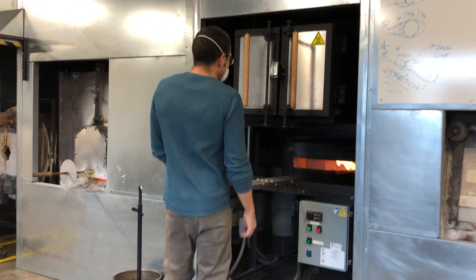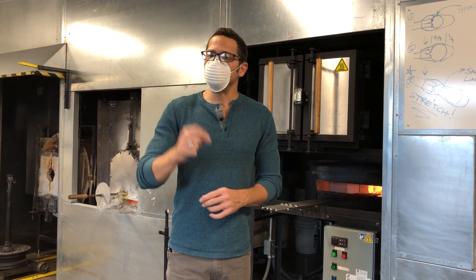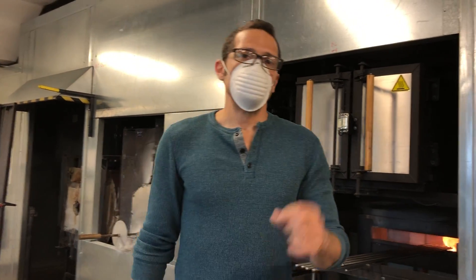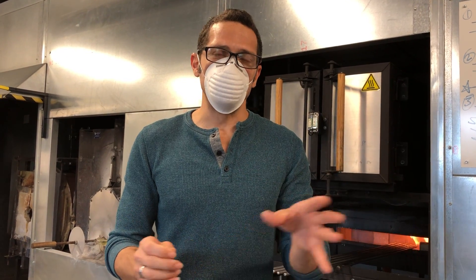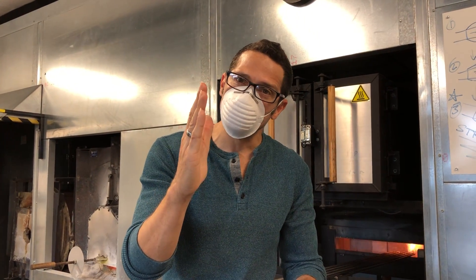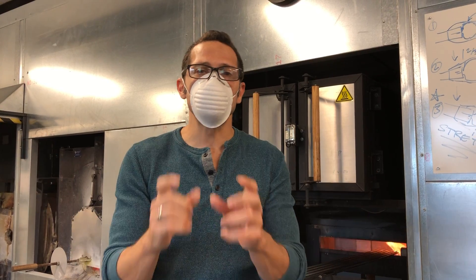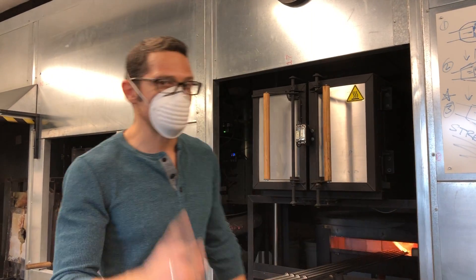I don't need to do anything to make this work. The only thing I'm going to be careful about when I'm at the furnace is making sure I don't gather too much glass. Even if I could make a good shaped puntee but have too much glass, that glass is going to have a lot of heat, and if I'm trying to stick it to the bottom of a delicate piece, the sheer volume of heat can weld it on. A puntee — if you're a flameworker you know this term — a puntee is a cold seal. It depends on the bottom of the piece being cold and the tip of the puntee being hot. That difference in temperature is going to allow it to break off when you're done. So even if I make the world's best puntee, but the bottom of my piece is too hot when I stick it on, it's still going to weld on forever. So timing — all those things matter. But if you have everything else right, you've indented the bottom of your piece, it's not too cold — here's how you make a simple good puntee.